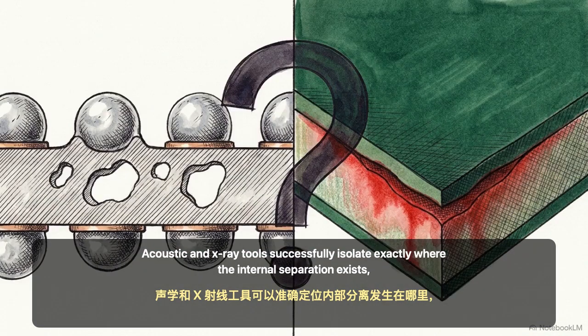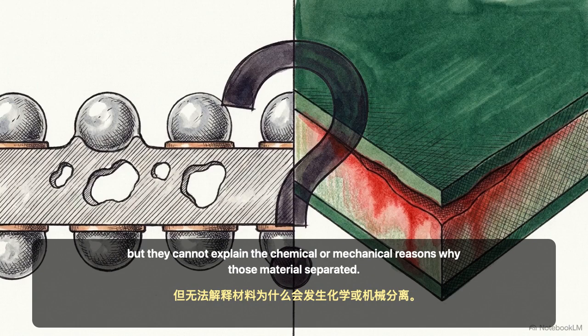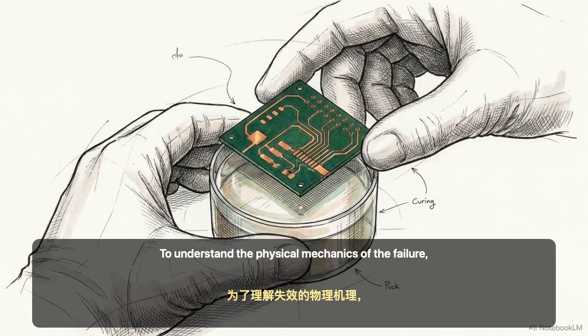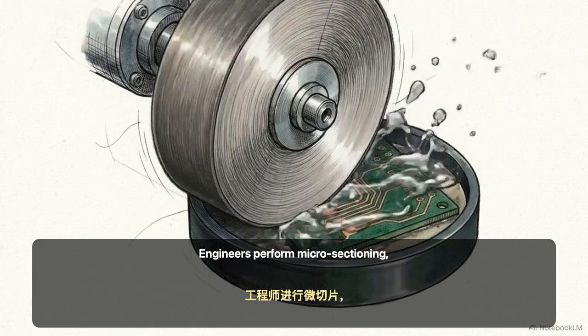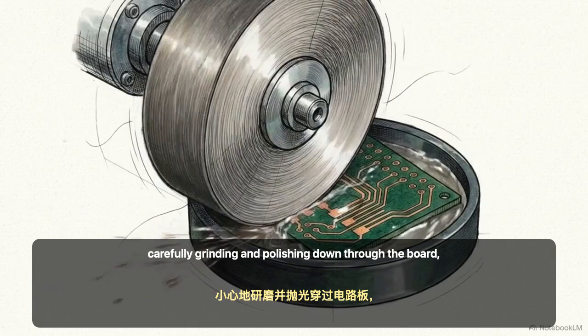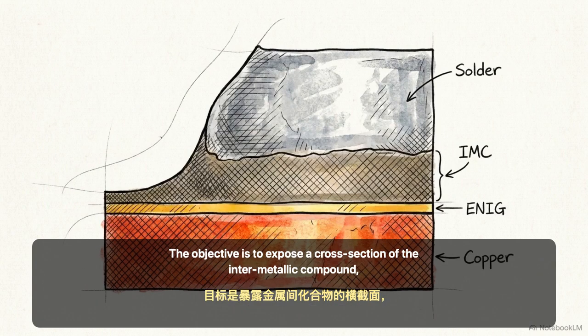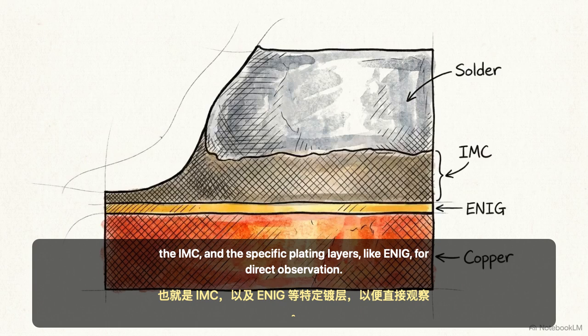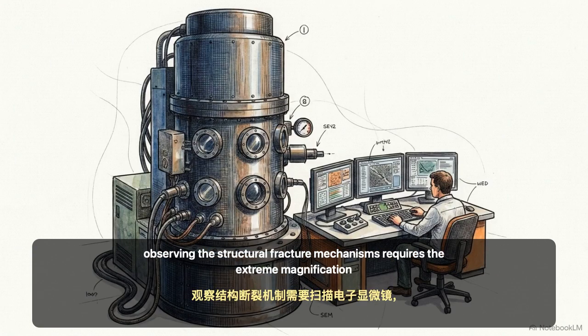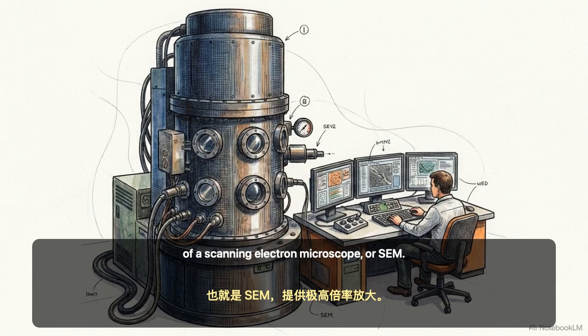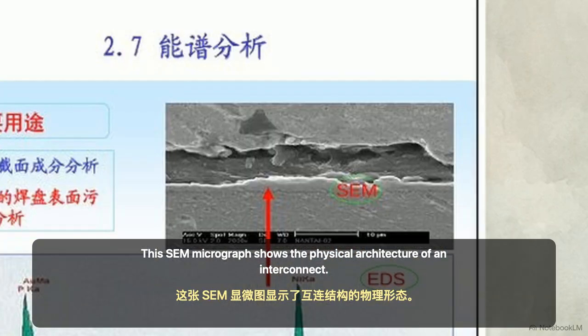Acoustic and X-ray tools successfully isolate exactly where the internal separation exists, but they cannot explain the chemical or mechanical reasons why those materials separated. To understand the physical mechanics of the failure, the analysis moves to destructive testing. Engineers perform microsectioning, carefully grinding and polishing down through the board to physically slice directly into the targeted defect. The objective is to expose a cross-section of the intermetallic compound, the IMC, and the specific plating layers, like ENIG, for direct observation. Because these layers are microscopic, observing the structural fracture mechanisms requires the extreme magnification of a scanning electron microscope, or SEM. This SEM micrograph shows the physical architecture of an interconnect.